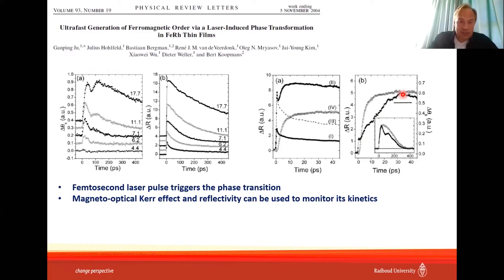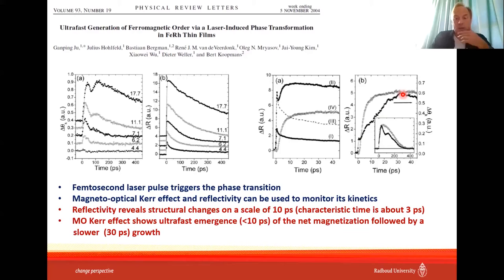Also, we can count as good news that the magneto-optical Kerr effect and reflectivity can be used to monitor the kinetics of the phase transition. And the interesting findings were that reflectivity reveals structural changes on a timescale of 10 picoseconds, and the characteristic timescale is about 3 picoseconds. Then the magneto-optical Kerr effect shows first an ultra-fast emergence, on a timescale much faster than 10 picoseconds, and then a very slow growth on a timescale of 30 picoseconds. What happened further?